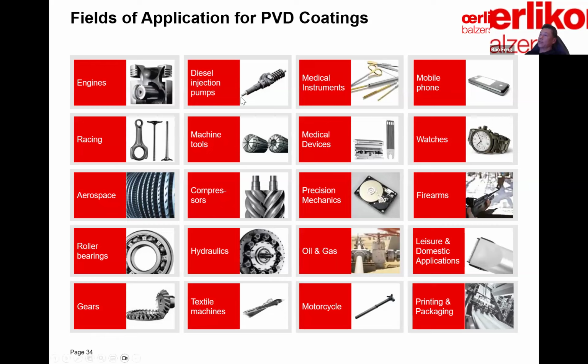And also diesel injection applications for injectors and pumps. I would say 20 years ago, this system would work fine without coatings. But with the new emission regulations and the requirement for higher efficiency, these components were made with much tighter tolerance. We're talking about a few microns. So metal-to-metal contact will instantly cause a seizure. So the DLC type of coating is kind of a standard solution for this application. And also engine valves, where you have thermal erosion, adhesions, and those issues can be mitigated by chrome nitride type of coatings, which offer better performance than something like hard chrome.